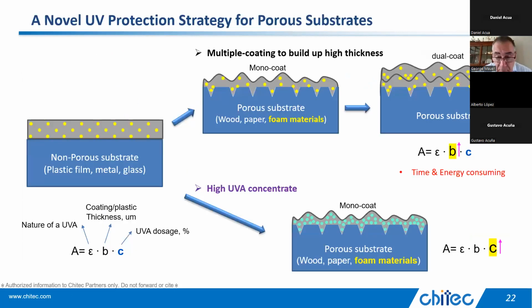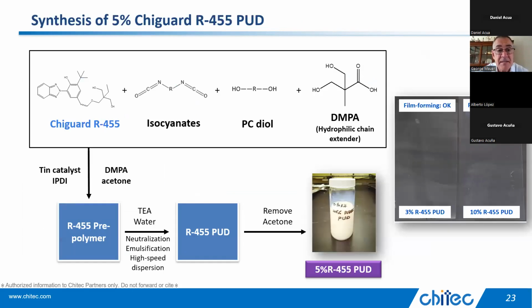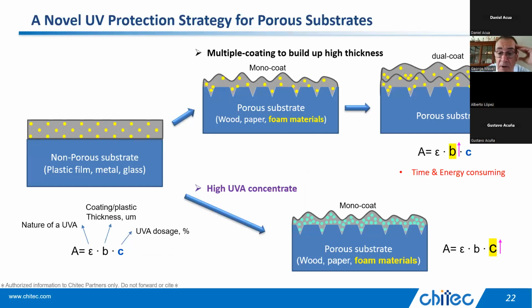The concept here is really just where's R455? In this case, if we make our polymer with R455, you can put in 10%. In this particular case, we did 10% of R455 into the polyurethane dispersion. So that's very concentrated in UV absorber. And the green dots are supposed to represent R455 molecules in the polymer system. The idea is that you can make the UV absorber more concentrated in the film so that at a thin film, you can absorb more light.